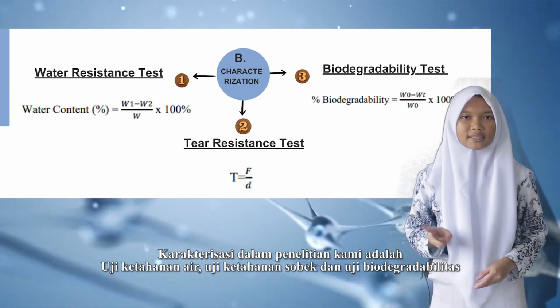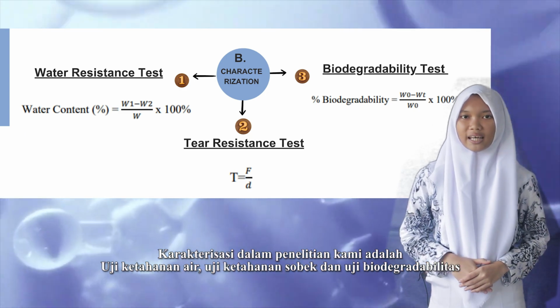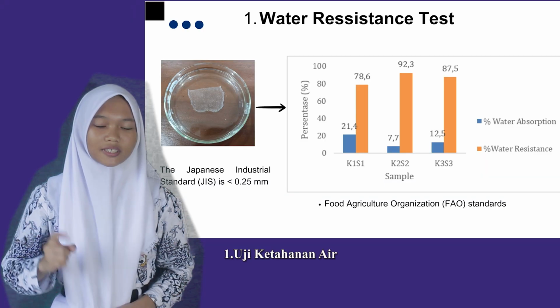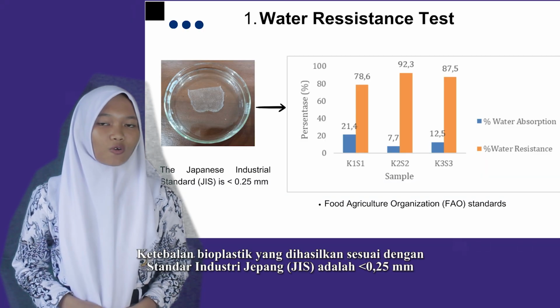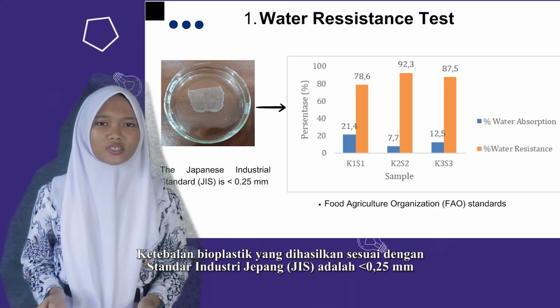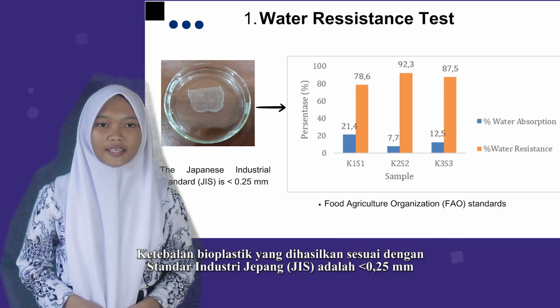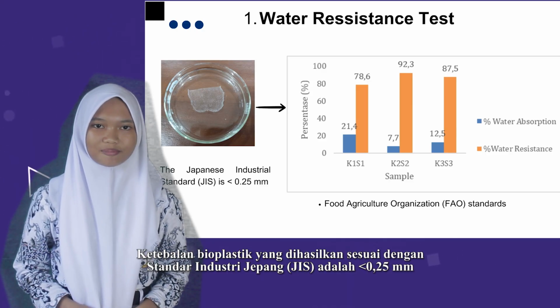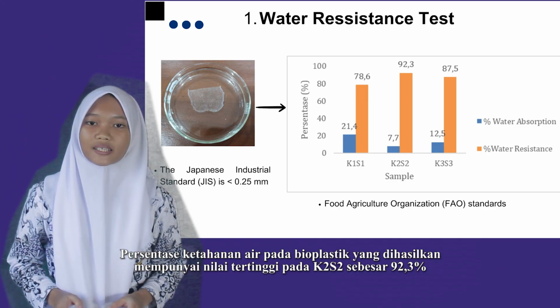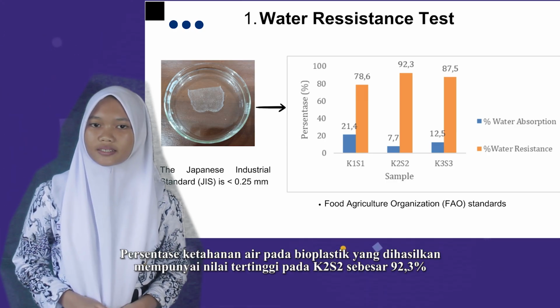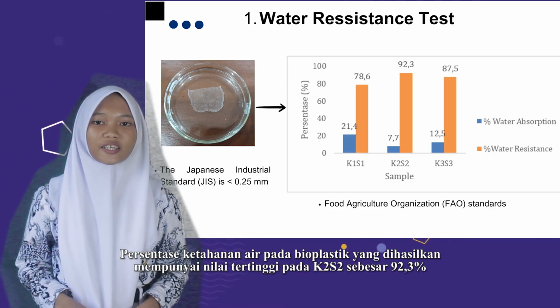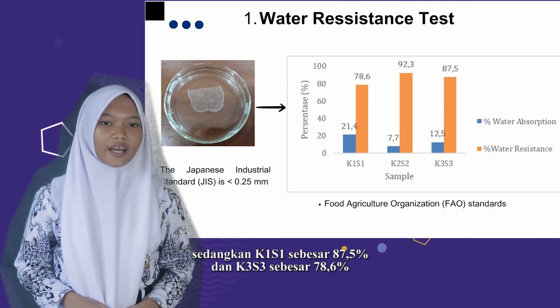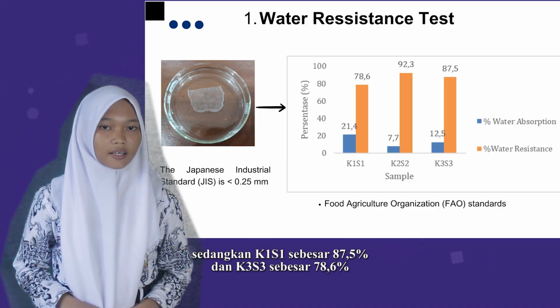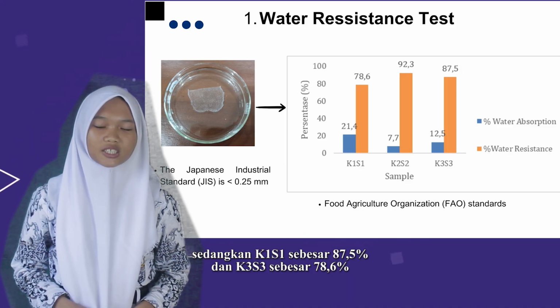Characterization in our research is the water resistance test, tear resistance test, and biodegradability test. The results and discussion in our research are: first, water resistance test. The thickness of the bioplastic produced is in accordance with the Japanese Industrial Standard, which is less than 0.25 mm. The percentage of water resistance in the bioplastic produced has the highest value in K2S2 at 92.3%, while K3S3 is 87.5%, and K1S1 is 78.6%.